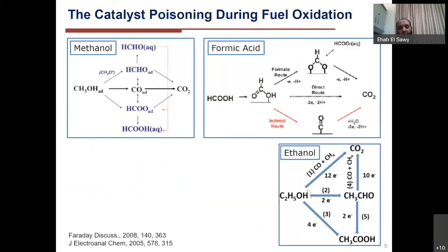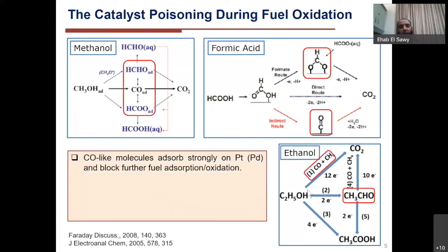So this is the mechanism for the majority of the fuels that are used in the direct liquid fuel cells: the methanol, formic acid, and ethanol. And as you could see, all of these fuels have carbon monoxide-like molecule formation as an intermediate during the oxidation. And these intermediates cause a very strong adsorption on the surface, hindering the further oxidation of the new fuels and blocking the surface for further oxidation.